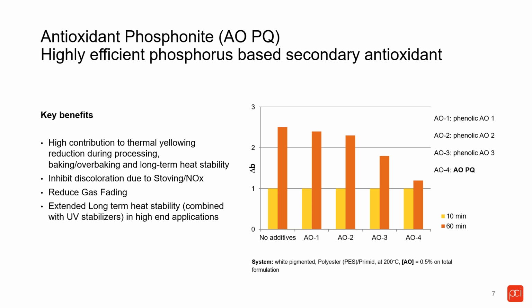And antioxidant PQ, which is a high efficiency phosphorus-based antioxidant, is really providing just a slight increase of yellowing compared to the other phenolic antioxidants. So it's very important when we do our baking that we also check the different chemistries of the antioxidant to ensure we get the best performance.